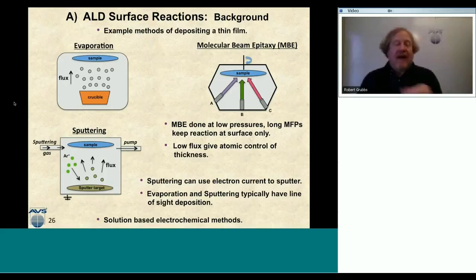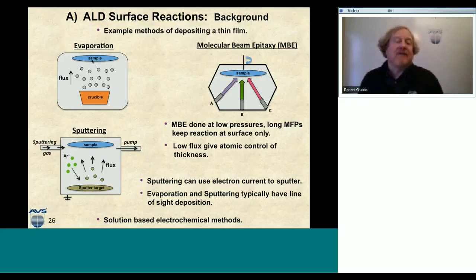Evaporation is just when I have maybe a piece of tantalum foil or a tantalum boat, and I put a low melting point metal in there, and I run electric current through it, or I heat it up, and we get molecules that increase their vapor pressure, and they go into the gas phase, and then they deposit on a colder sample substrate that might be mounted right above the sample. This is typically a line of sight technique where molecules will just leave and then ballistically go and then just stick wherever they hit.